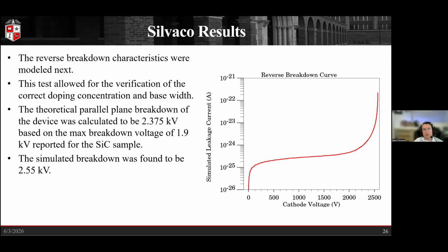Next, we wanted to estimate the reverse breakdown characteristics and make sure that that aligned relatively well with the characteristics that were provided to us. So when we actually looked at the breakdown curve provided by the manufacturer, it was actually about 1.9 kV rather than the 1.7 kV nominal value.